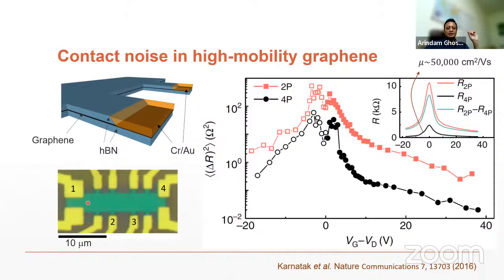Okay, so that essentially eliminates what you call contact noise, because we realized that it is the metal graphene contact that can lead to an additional source of noise, because the metal damages graphene locally, and that leads to breakdown of screening and very large noise. So we found that when you do that, the noise again comes down. So instead of a normal invasive probe geometry, if you use this kind of non-invasive Hall bar geometry, then the noise comes down. Okay, and it comes down by another order of magnitude.